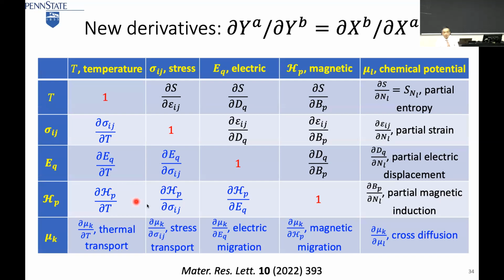For example, the Seebeck coefficient. People always think the Seebeck coefficient is a kinetic property. People use kinetic methods to calculate it. It turns out the Seebeck coefficient is the derivative of the chemical potential of the electron with respect to temperature. That's the Seebeck coefficient. So we got this idea, we published two papers, and we predicted the Seebeck coefficient without the Boltzmann method.